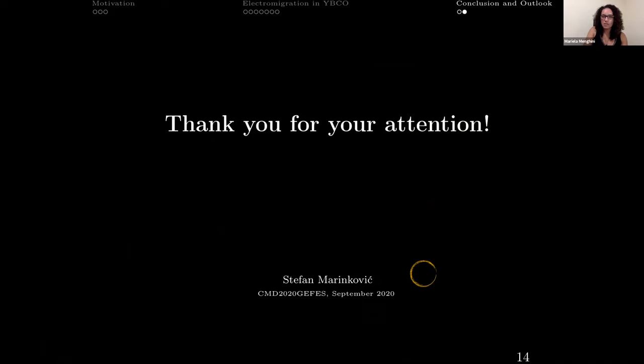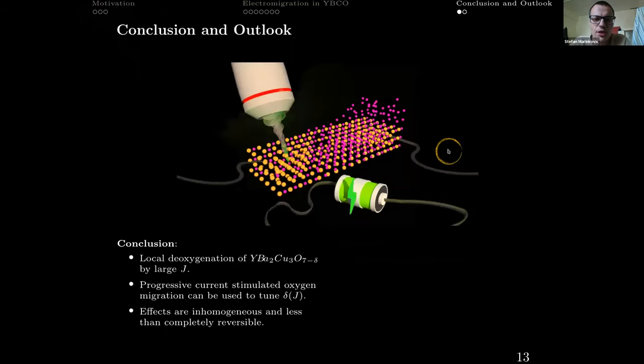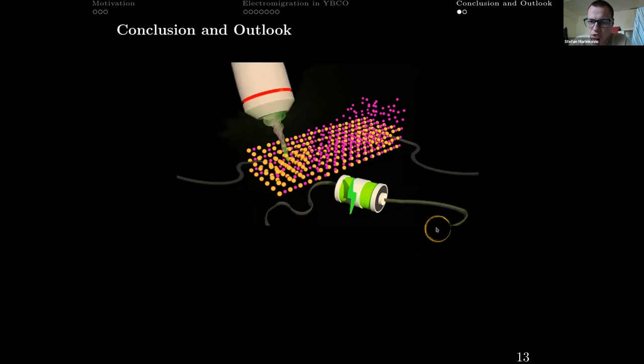Yeah. So you just mentioned at the end that you want to distinguish between A and B direction. So in the experiments that you've done, do you know which is the crystalline direction of your film or not? Yes, I know that they are C aligned, but the A and B directions are not completely distinguished. There are grain boundaries. We would need a miscut film or essentially an untwinned film of YBCO, where we could use different directions of the devices to compare essentially the two. And similarly to Anna, we have seen very, very large differences compared to the expected length of diffusion in our films.